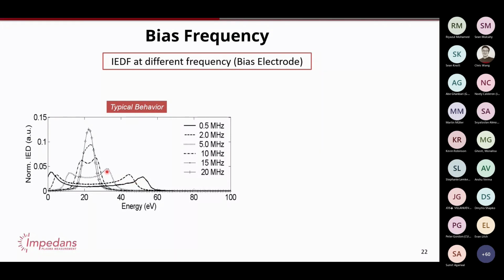But if you wanted such high energy ions at 60 megahertz or whatever, you would have to put in a huge amount of power to get the DC voltage that you want in the electrode. Whereas if you use a really low frequency like 400 kilohertz, these are all at the same power, at a much lower power you get much higher energy ions. So by using 400 kilohertz, you can get the huge ion energy you need to do your process without needing 90 kilowatts into your tool and melting the wafer or burning the tool.